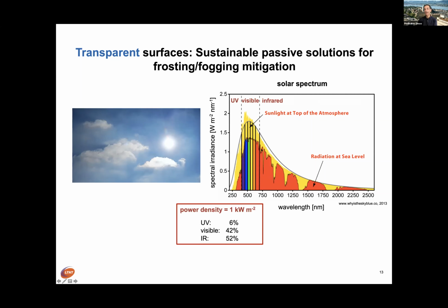But a lot of the energy of the sunlight is contained in the infrared, all right? Almost 50% of the energy of the sunlight is contained in the infrared, and then we decided to see if we can design a surface that absorbs radiation selectively in regions. That is, it does not absorb well in the visible, and so the visible stays transparent, but absorbs very well in the infrared. And if we do that, then of course we absorb the infrared to elevate the temperature of the surface, and we avoid nucleation for condensation or even later on frosting.